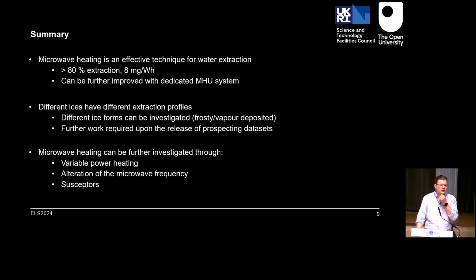I think that's kind of coming down to the frequency point I made right at the end there, where I think the frequency at the moment is set up for better heating of the simulant rather than the ice. However, the problem with that is that where ice is most susceptible to microwave heating, you're at a frequency where your penetration depth is really small. So there needs to be a systems architecture trade-off there between how far into the sample you want to heat, especially if we are using an open microwave straight onto the surface. If the ice is tens of centimeters down, there needs to be that trade-off between what we're doing.